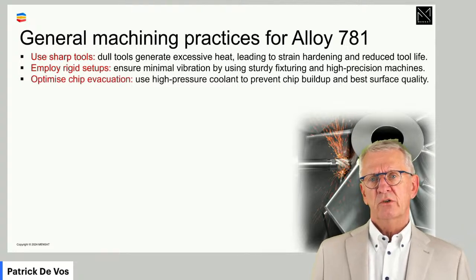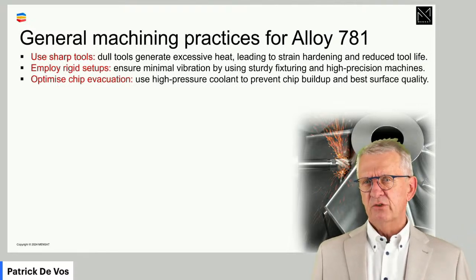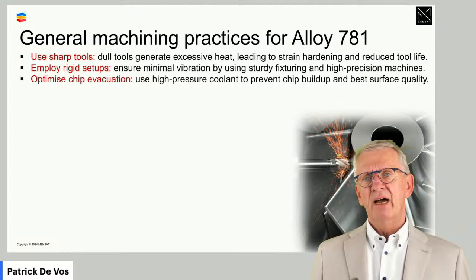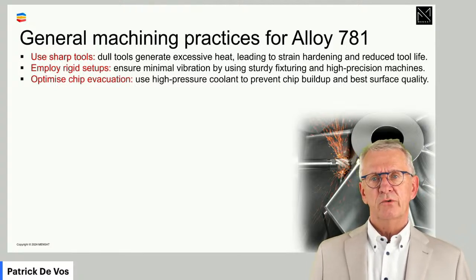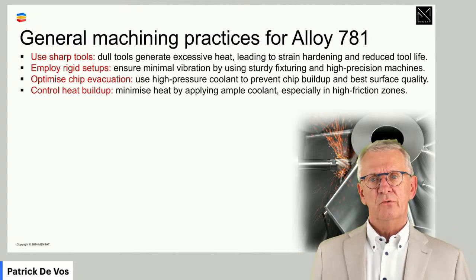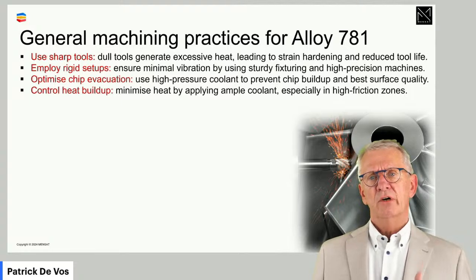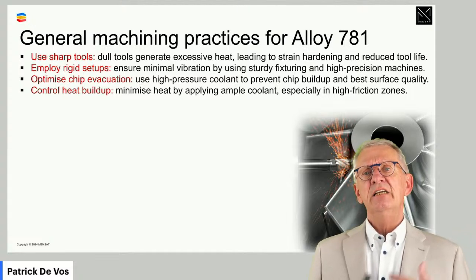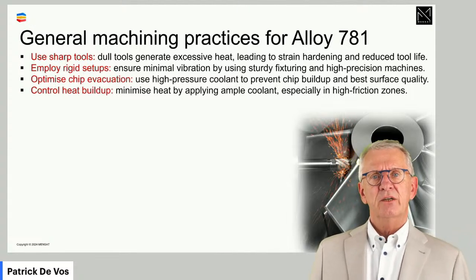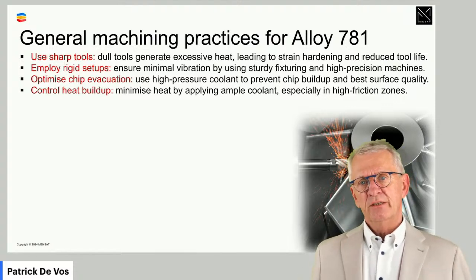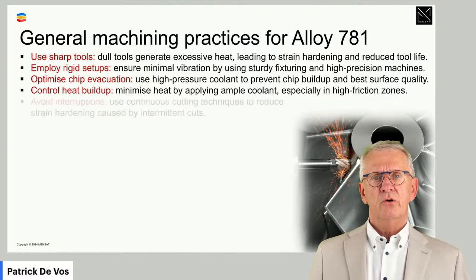Chip evacuation, because as we work with positive geometries, chips will show a tendency to be long. That means that we have to manage those chips in the best possible way and evacuate them in the best possible way from the cutting zone. Heat generation, that's the thing to worry about. Make sure you do whatever possible to generate as little heat as possible, and the heat which is generated evacuated in the best possible way. With some thicker chips, cooling methods are important here, and so on.